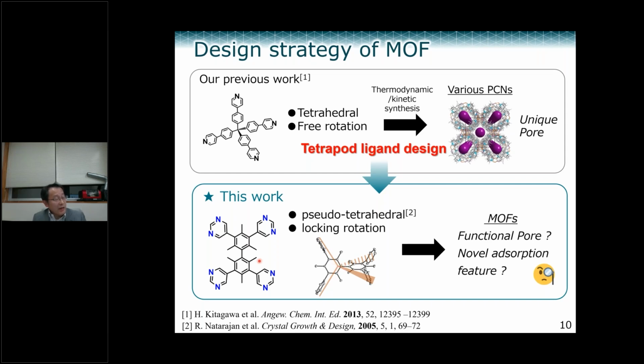The feature of this ligand is that this rotation is suppressed because of a steric hindrance between this methyl group, so you cannot rotate this group. It is a relatively rigid group. And as a coordination site, we introduce a pyrimidine group here. Then what kind of MOF can we get? So we tried.